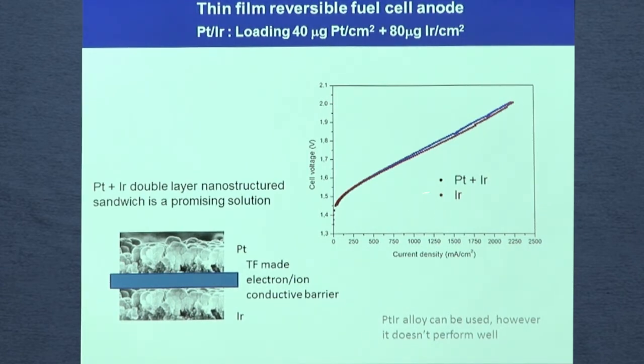Pure iridium thin films give this performance and this activity. And by adding platinum, you can see that we have almost the same results. We added platinum not in the form of an alloy. This is what people are trying to do, but an alloy is not very active. We make a special procedure by separating a multilayer or double layer of platinum and iridium by an electron and ion conductive barrier. Which means that by adding platinum, it's not better, but it's not worse. It's quite pure iridium.